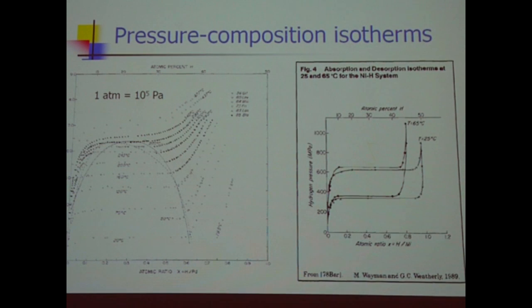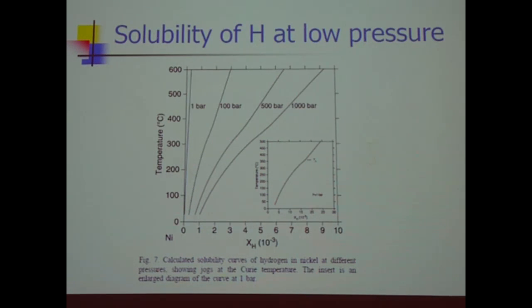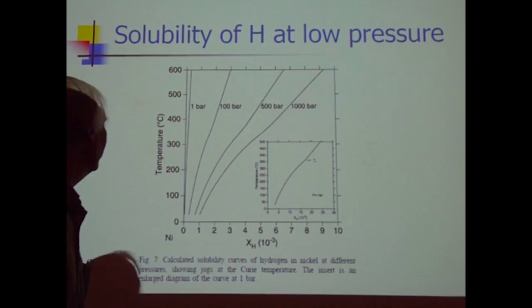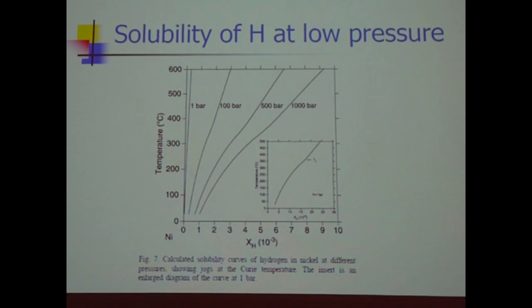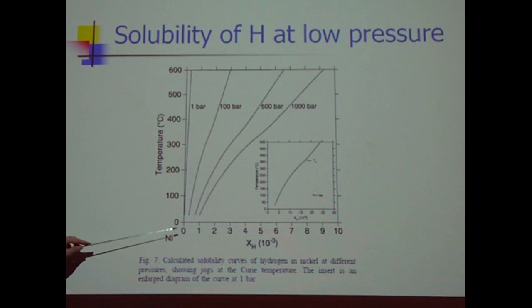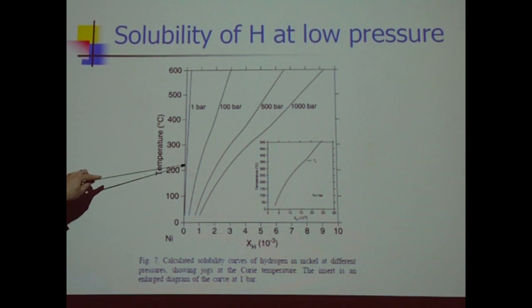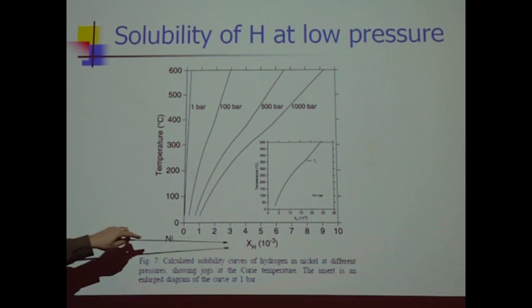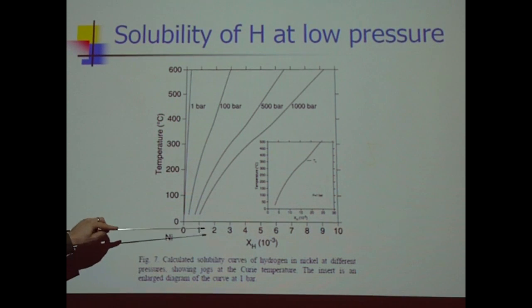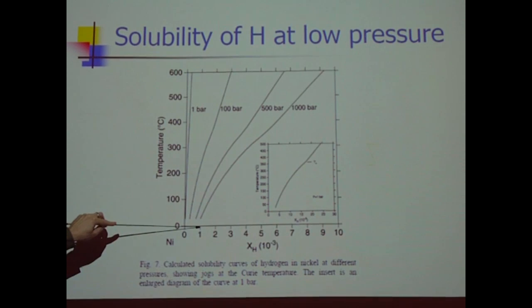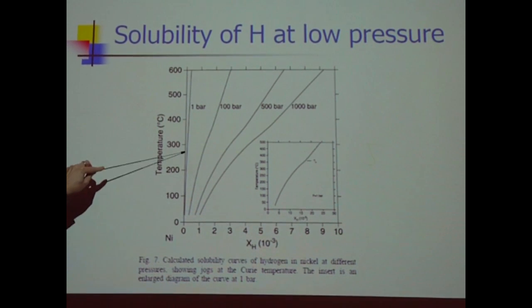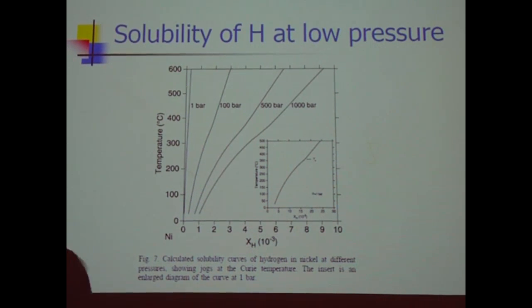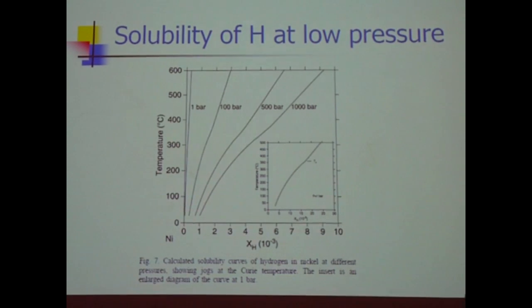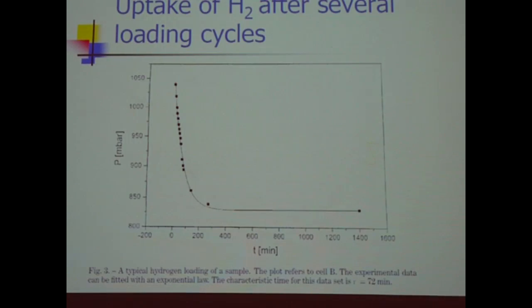So we talked about the pressure composition isotherms, and if you look in the literature and you say, well, how much loading do you expect at the temperatures that are under discussion? Near 1 atmosphere, you don't expect much loading. So this is loading in units of 10 to the minus 3. Here's 1 in units of 10 to the minus 3. And here's numbers which are a small fraction of 10 to the minus 3. So you'd expect bulk loading in nickel to be very low.